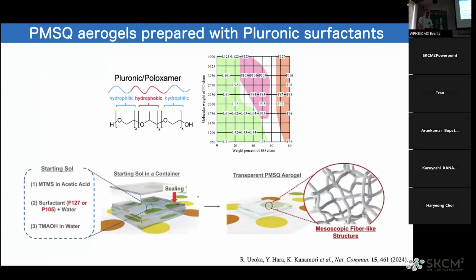We are now updating the process of aerogel synthesis by using a different surfactant. In the previous process, I didn't say, but we used a cationic surfactant to prevent phase separation. Then we got a good aerogel showing flexibility against compression. Now we are using a polymeric surfactant. It is called Pluronic or poloxamer.